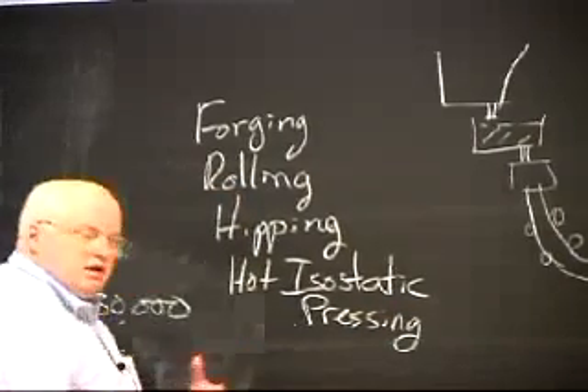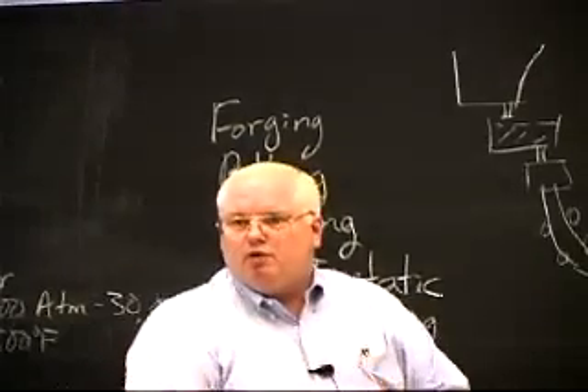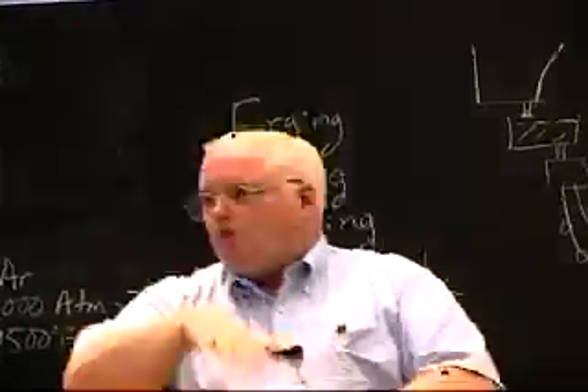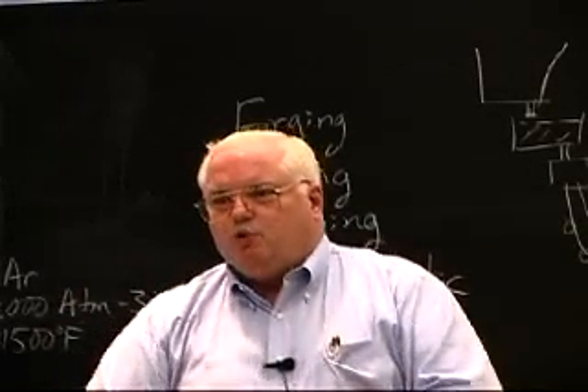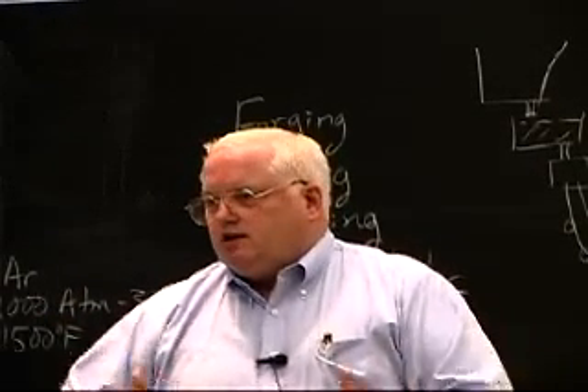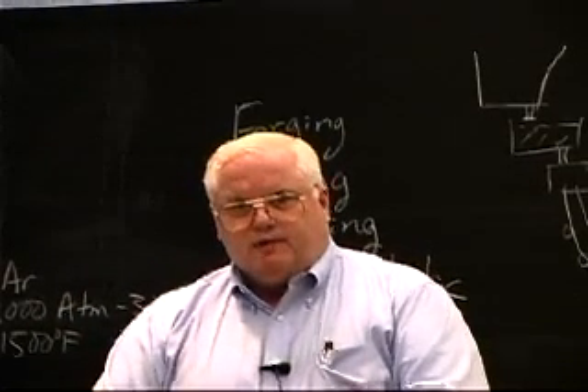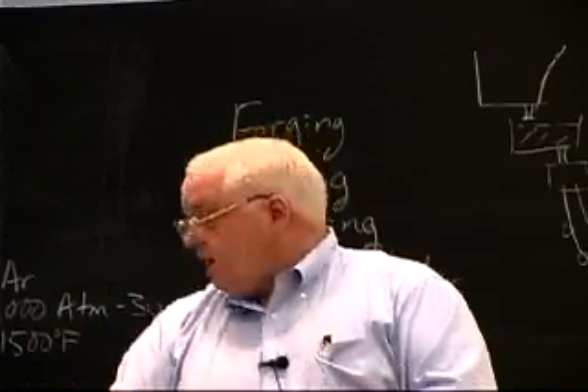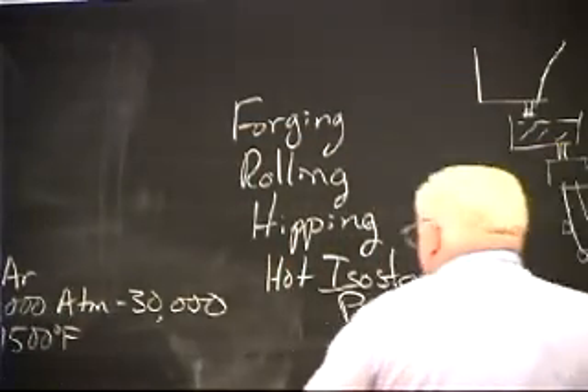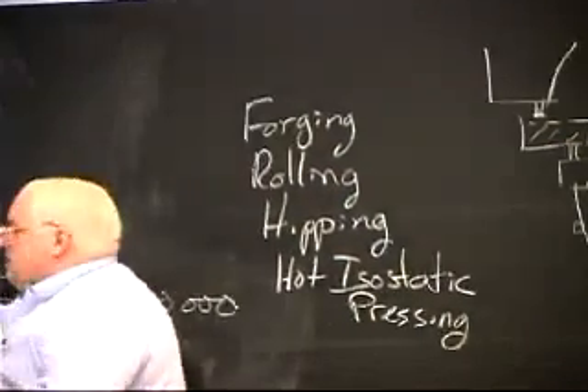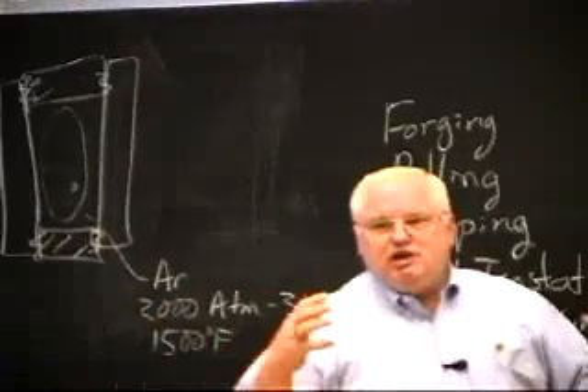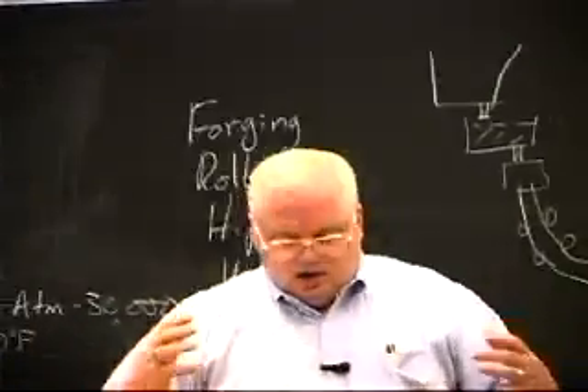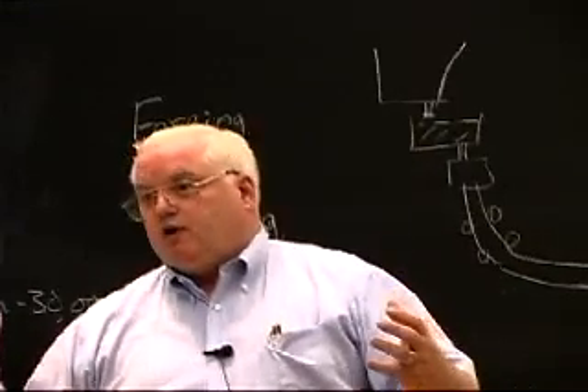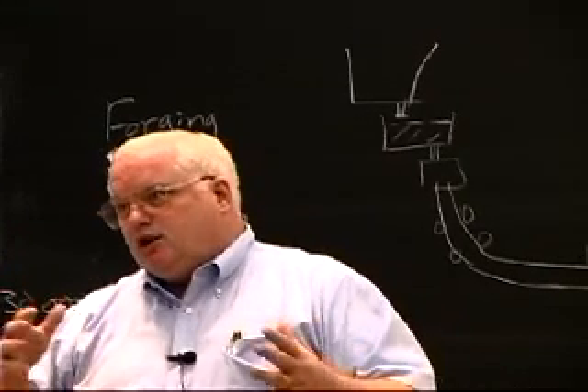It's isostatic because you have pressure, equal pressure from all directions, whereas in rolling, you're squeezing, and forging, you're squeezing from one direction. Here it's isostatic. It's just like putting it at the bottom of the ocean, right? You're squeezing it from all directions while it's hot, and you can squeeze out the defects. So typically now, we may cast in a near net shape a titanium turbine disc for an aircraft, and then take it over to the hip unit.